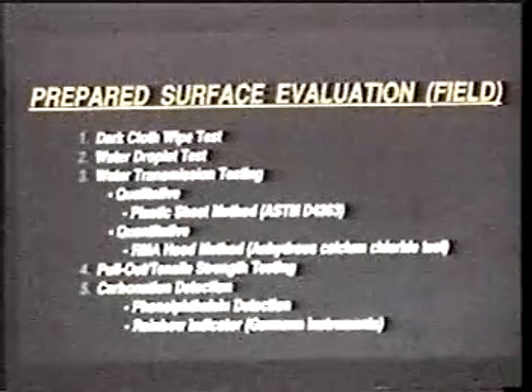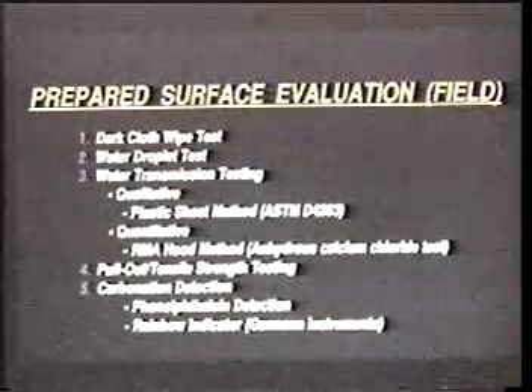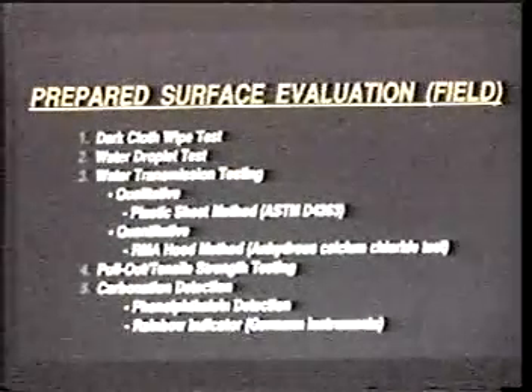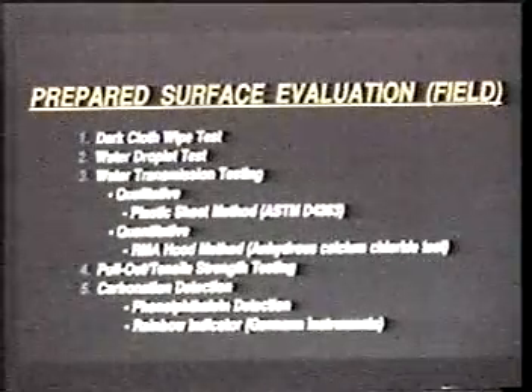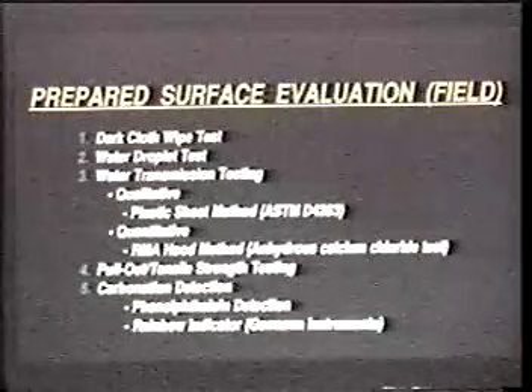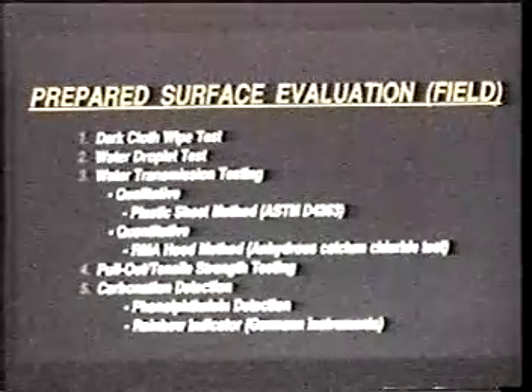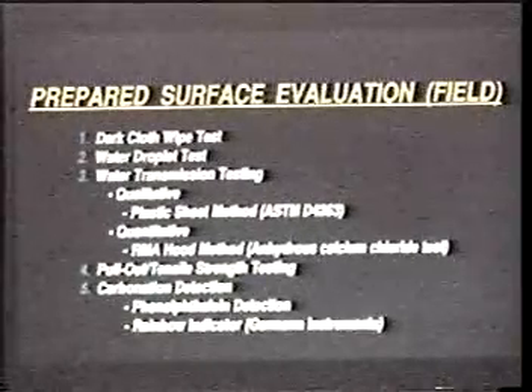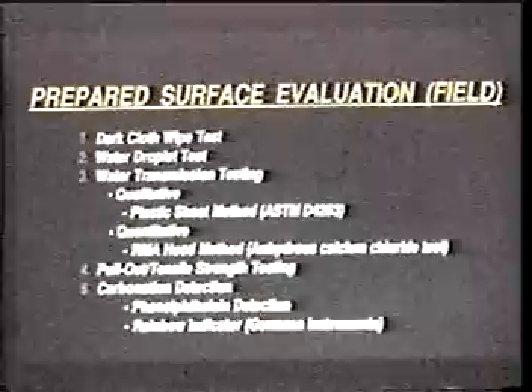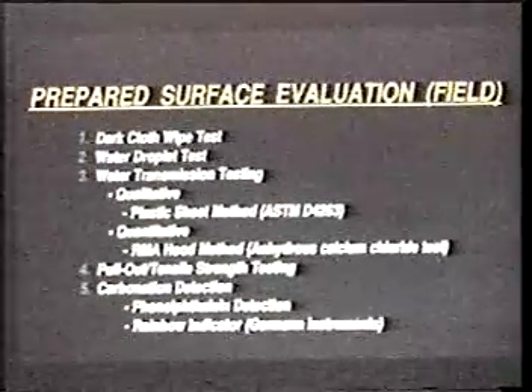which is the so-called direct pull-off tensile strength test, which initially was actually used for evaluation of the condition of the concrete, the pull-out strength of the concrete. If you have any doubts, as an engineer or a contractor, that maybe the existing concrete by its nature is not adequate to develop a certain bond, 200, 300, whatever PSI bond, it is always better to be on the safe side and check the strength of the prepared surface by this pull-off test before it receives the repair material. If you are not achieving it because of some problem, whether with the existing material or with the workmanship of the contractor, you don't have to remove it later on.